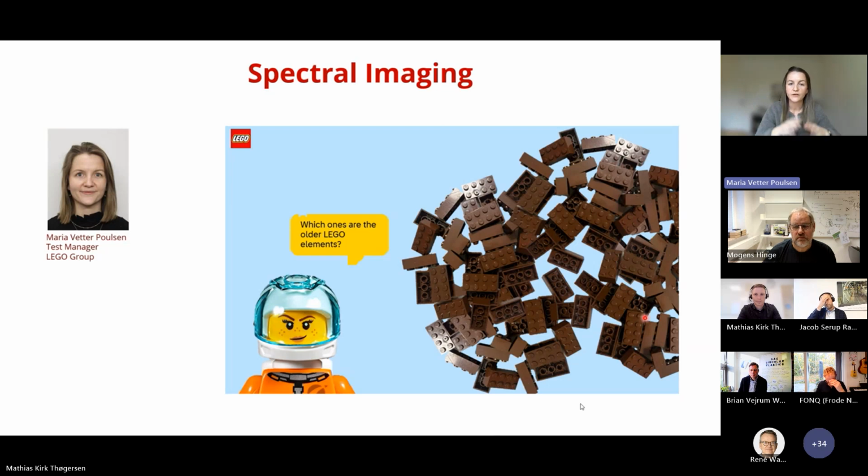We also took the XRF, going through all the inorganic compounds in our master batch to see the variation change in master batch over time. The spectral imaging system that we were using operated from 395 to 700 nanometers. That means we capture some in the visible regime, and therefore we also thought the input from the master batch, hence the XRF, would be of importance here. But very meticulous work. One element, one number, all analysis. So very specific conditions for what you're looking for and how you are sorting this.